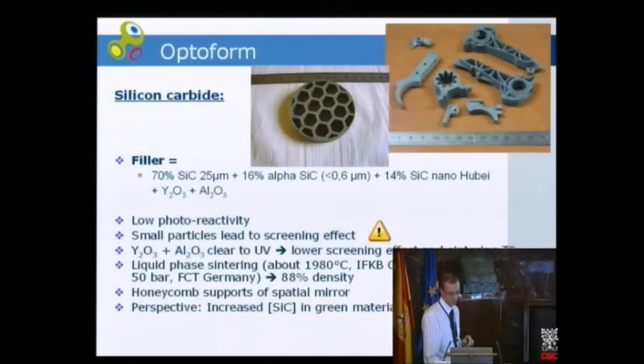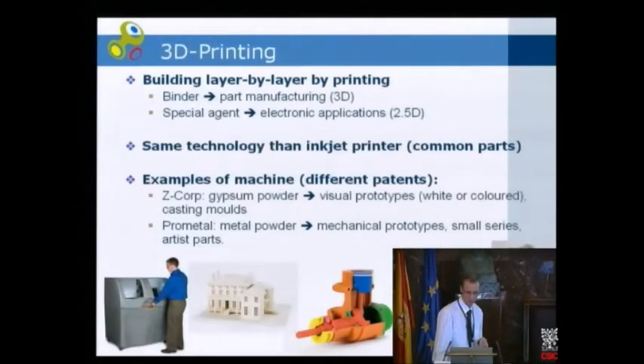They have been sintered at about 2000 degrees at IFKB or IFCT in Germany. The example of part we made are shown here. We have several technical parts, and this part was made for NanoCare project. It was a honeycomb support for a spatial mirror, and we reached final density of 88%. This was not very bad, but not very good too. Because we can increase this final density by increasing the concentration of filler inside the paste. So it will perhaps increase the final density this way.